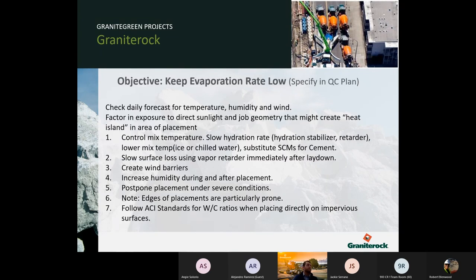You want to keep the evaporation low. So ways to be successful using green concrete and not have plastic shrinkage is to check the forecast, temperature, humidity, and wind. Factor in exposure to direct sunlight. The job geometry might create a heat island in an area of placement, so windows bouncing light into a certain area. A good way to help fight this off is to control the mix temperature.